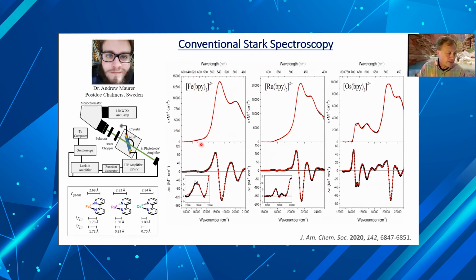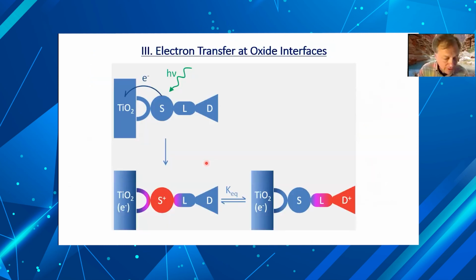One of which was in the ground state absorption of these molecules, at long wavelengths, there's very little absorption for iron and ruthenium, but for osmium, there's a very intense band, and that's due to a singlet to triplet charge transfer absorption, or it's been assigned that way. The bottom line is that in Stark spectra, they're much more pronounced, and we're now trying to figure out why. So I'm a little long-winded here. I'll switch over to this story a little more quickly.